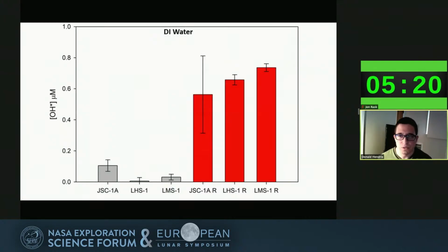Here are the results of reactivity in DI water. R denotes the heat treated and reduced samples, and we highlighted the results of the reduced samples in red. As you can see, heat treatment and reduction of these samples leads to a large increase in OH radical generation compared to the not reduced samples in gray. This is very likely due to the presence of metallic iron, and it shows how drastic an effect the presence of metallic iron alone can have.